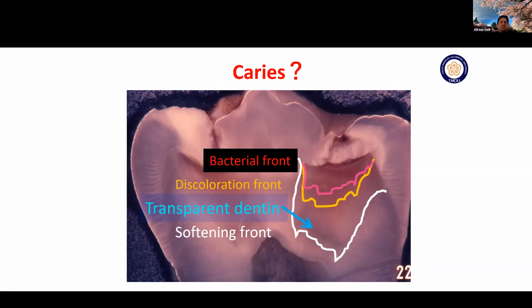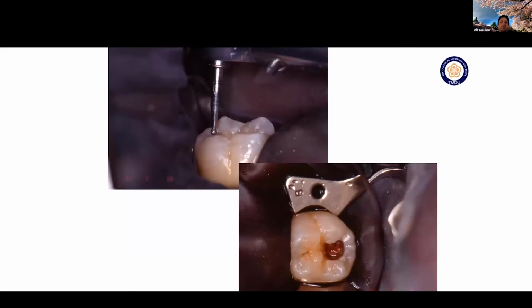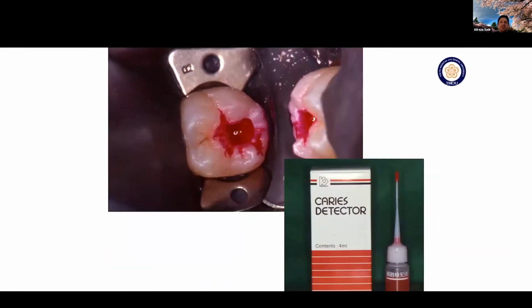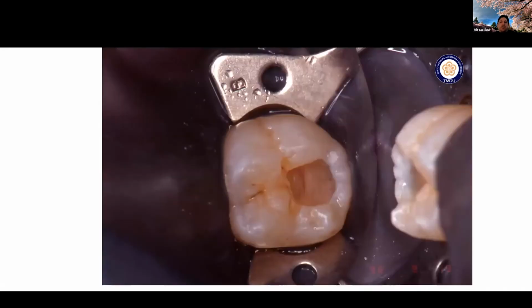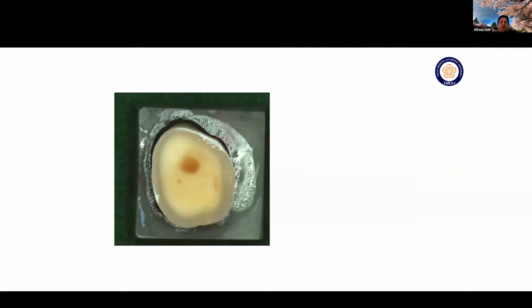But transparent dentin formation, this has been a subject to debate. But what we know is that the softening front is usually much deeper than the discoloration front and should not be exactly the basis for our caries removal. Okay, so the clinical use of caries detector dye can help you in removing the caries, right? Whether you're going to do a lining or not. But let's look at the permeability.